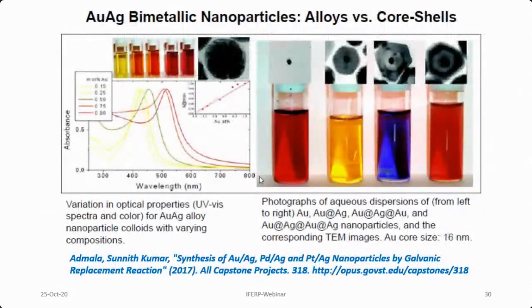Another work is what they have done. They have compared gold and silver bimetallic or alloy nanoparticles versus core shell nanoparticles. In one case, the gold is the core and silver is on the shell, and vice versa, and in another case both are mixed in different proportions, so they are essentially alloys, and in another case they are essentially core shell nanoparticles. Then they compared size and other properties as well as size dependent optical properties. So we can see this is also showing a very good